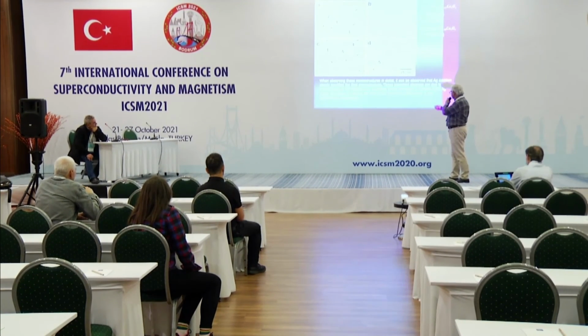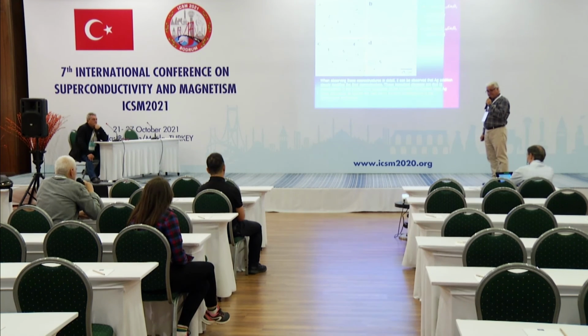Here you can see about micrometer. This part is silver addition. What were the initial powder properties of what you added to the initial mixture? Was it a silver powder or another form? Silver powder, yes. What was the particle size distribution of that powder? Metallic silver, not powder. It was metallic silver, but it was dissolved in acid, so you have it in the solution. So you took it into the solution. Yeah, acid solution. Yes, understood.